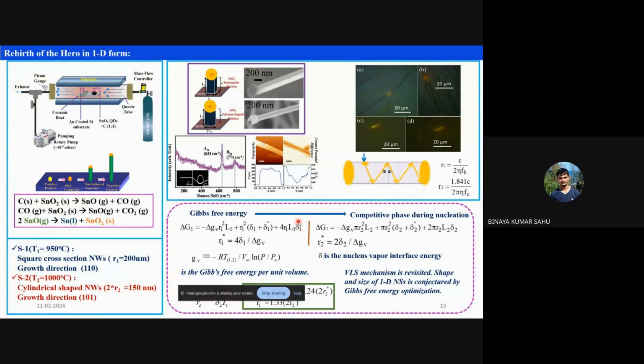So we did a simple calculation using thermodynamics, and we did the maxima-minima calculation, because anyhow we have to see the energy minimization. And what we find after a little calculation is that 950 degrees Celsius is always favorable for this kind of structure. The energy minimization will only happen with a square cross section at 950 degrees Celsius, whereas the cylindrical cross section is favorable at 1000 degrees Celsius. So this is the basic physics behind the alternation of the structure.